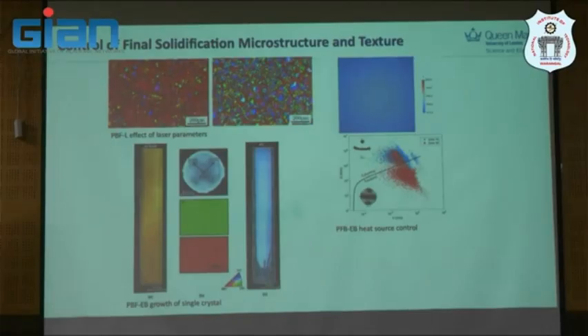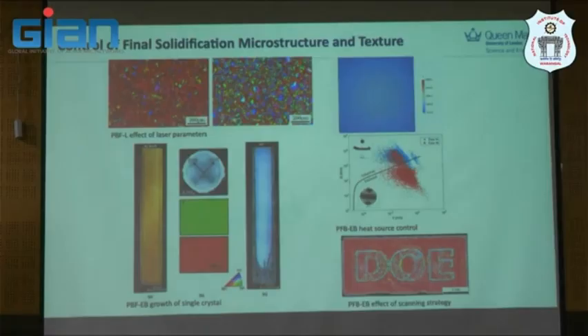The principle is something we can know, but in practice, this is something difficult. How can you get that condition? And this only happens in vacuum condition, which is the same for single crystal casting as well. They do it in vacuum. So that's why electron beam melting is possible to make this happen. But the maximum scale they get is 5 millimeter. I don't know now, probably with the latest development, they can get bigger components to do single crystal. But this is 5 millimeter thick, and this is one crystal grown. Impressive, yeah, by Professor Kroner at Erlangen in Germany.